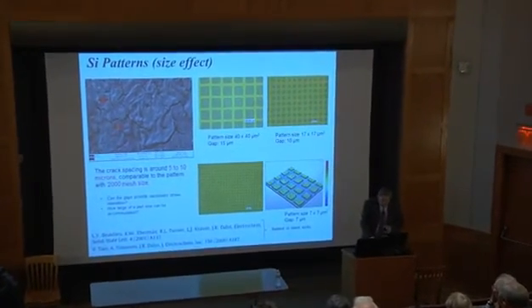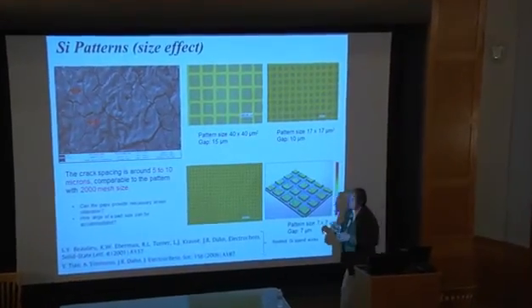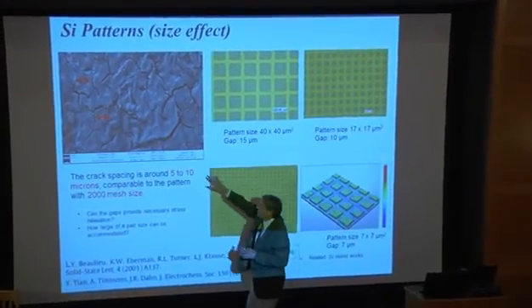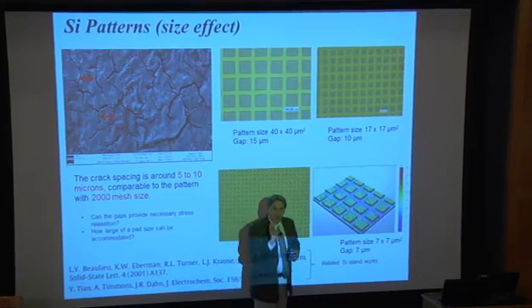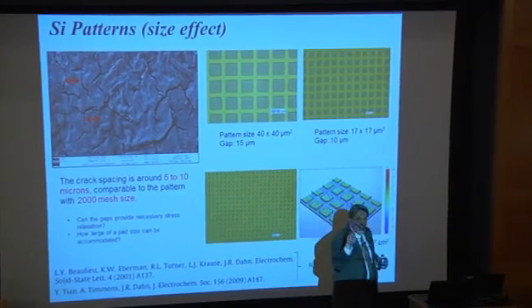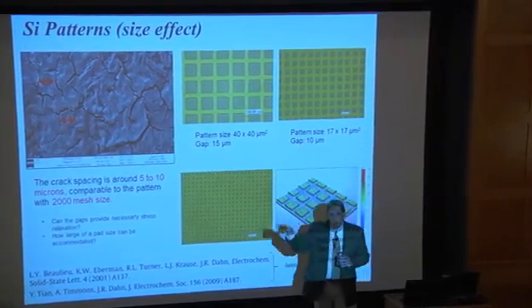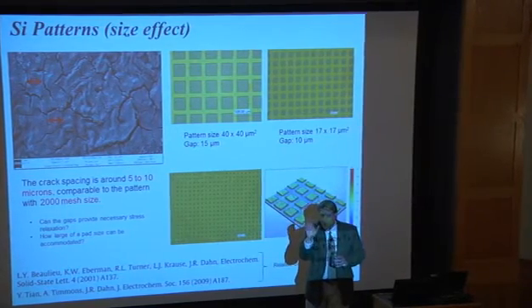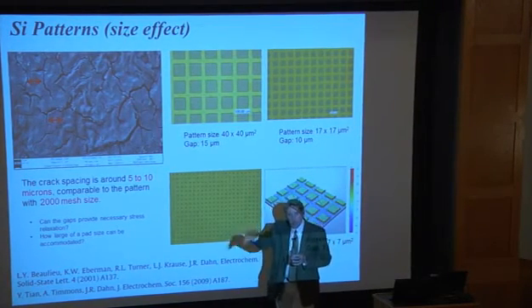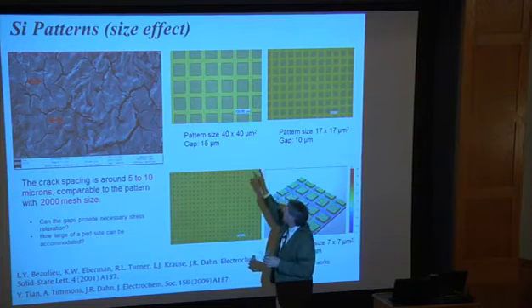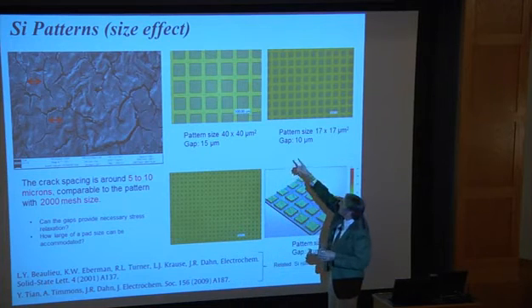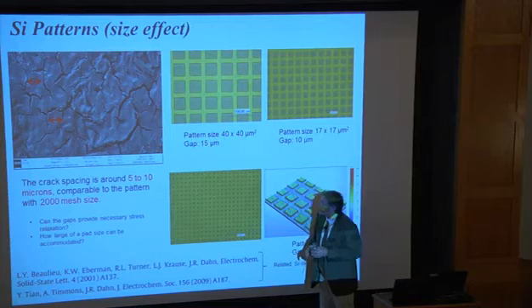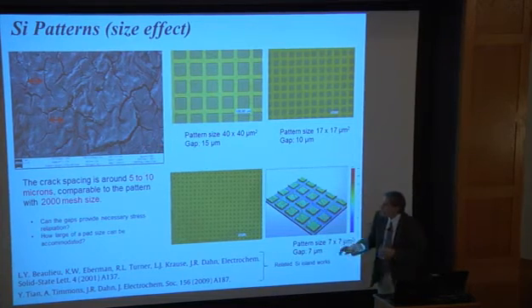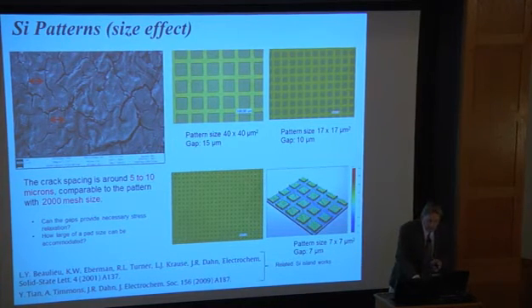So one of the things that you see in silicon electrodes, a pure silicon electrode shown here, is this pattern of crack formation where it looks like the cracks are forming about 7 micron characteristic dimensions. You almost can think of pads of active material with stress-relieving cracks around them. And that's partly why we decided, well, let's put in different pad sizes, but we'll terminate with a 7 micron pad and see if we can actually get enhanced cycling capability.